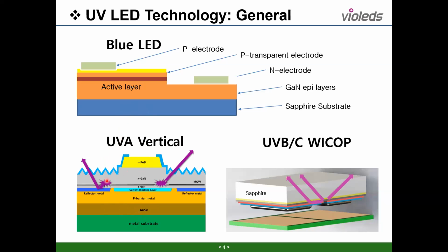Here the active layer is here, and when light is generated, it can first go through the surface very well because the surface is very roughened, so there is no total reflection effect. Another thing is that on the bottom side a reflector metal is disposed, so the light from the bottom can be reflected back to the top and have another chance at extraction. Compared to the blue LED, UVA is much more efficient, but it's a more expensive process.